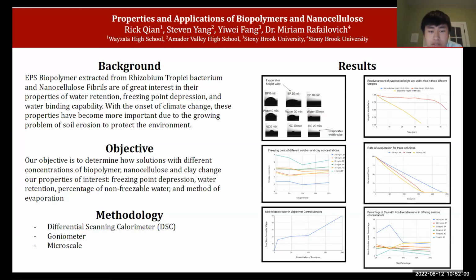Now let's take a look at the results. At the top, we have the graphs for the contact angle measurements. A goniometer was used to take pictures of water droplets on pure silicon wafers to determine how these droplets evaporate. Our analysis of the images shown in the top left indicates that the biopolymer evaporates height-wise, meaning that the height of the droplet decreases faster than the width, creating a coffee ring type shape.